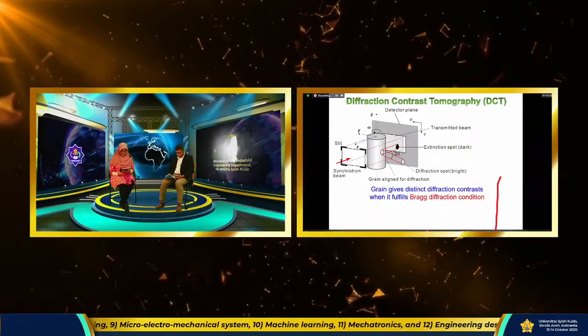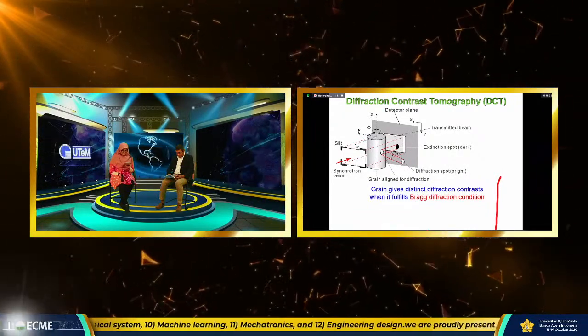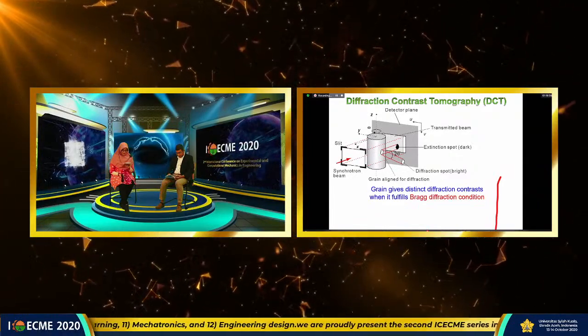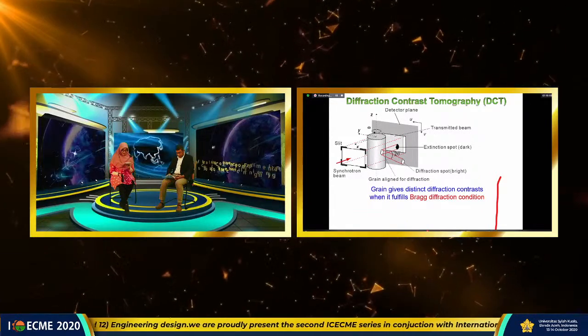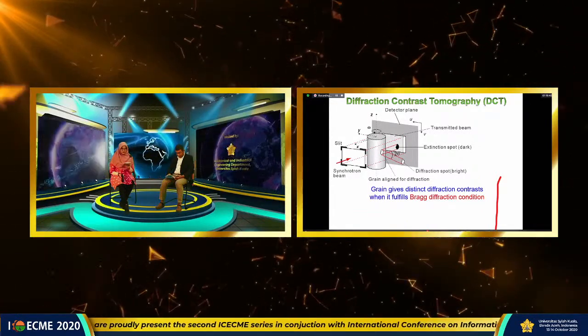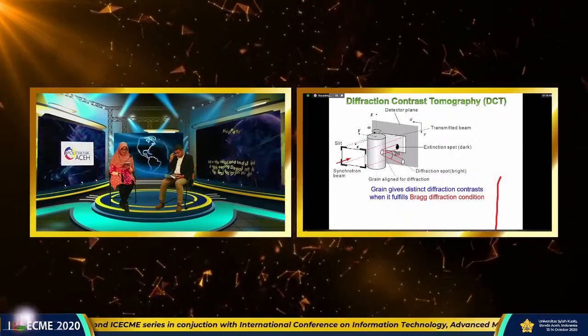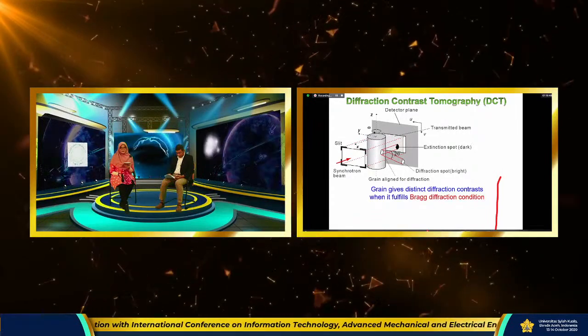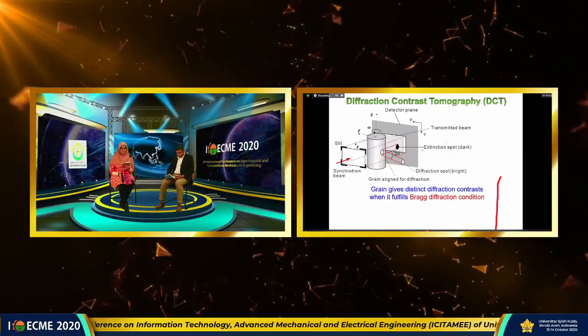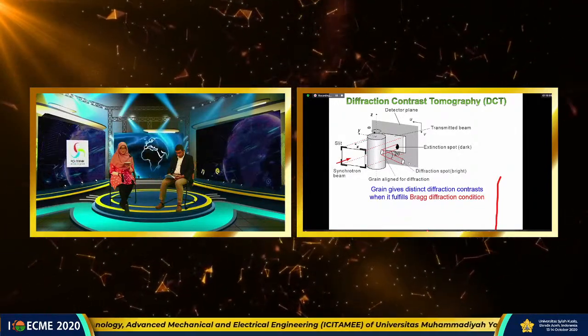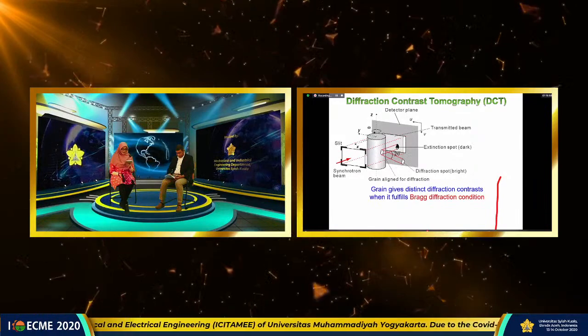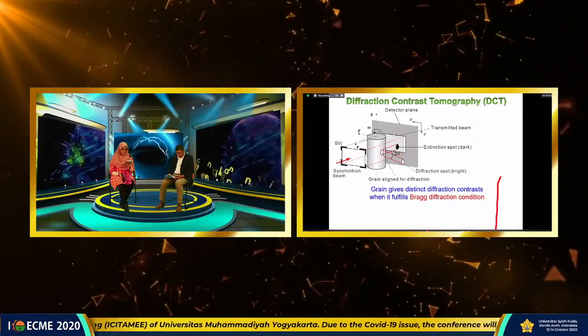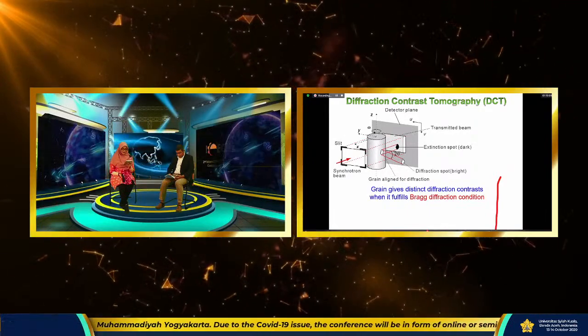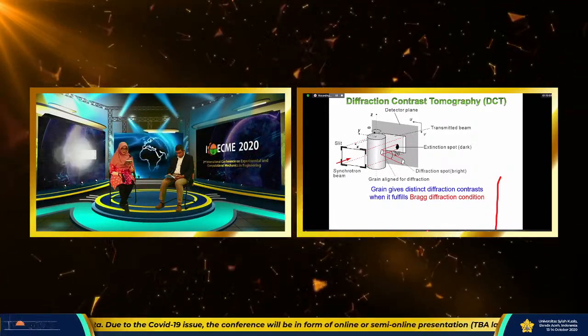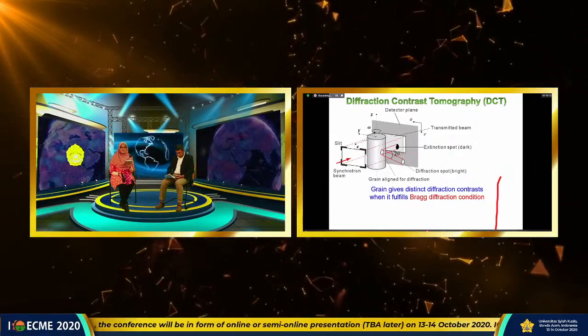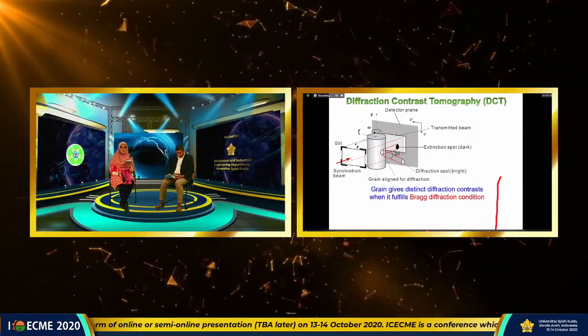Next, this one shows diffraction contrast tomography. During the rotation of a sample, we have an angle where the Bragg condition, or diffraction condition, is satisfied. So at that angle, we have a diffraction spot like this. At the same time, an extinction spot can be observed in the transmitted beam, which is set behind the sample. This spot is usually ignored and deleted by a median filter, but it plays an important role for diffraction contrast tomography.